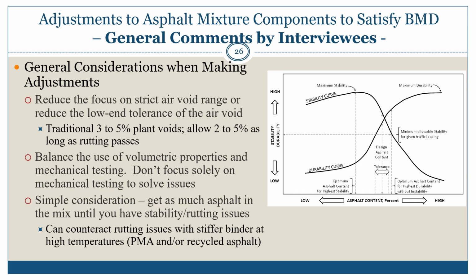Also, from a very practical consideration, if you think about the mix design that was conducted by Hveem back in the early 40s and 50s, you try to get as much asphalt into the mix as possible before you have a stability issue. And sometimes you can counteract some of these stability issues by using a polymer modified binder or a stiffer asphalt. So they simplified it: get as much binder as you can in the mix until you have a stability issue. And if you're not using a polymer modified binder and you still have a stability issue, change to a polymer modified binder. This should allow you to balance both the rutting and cracking properties of that mix.